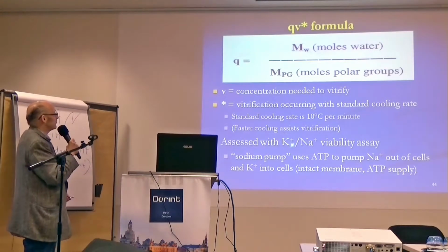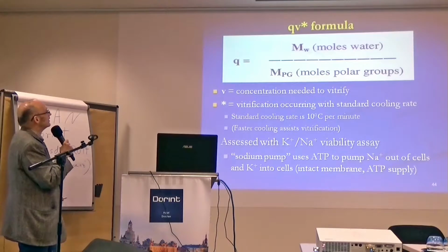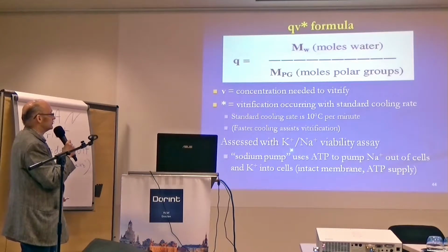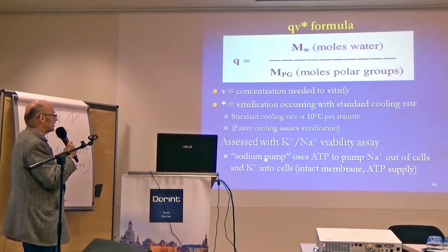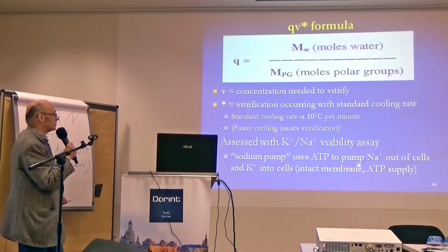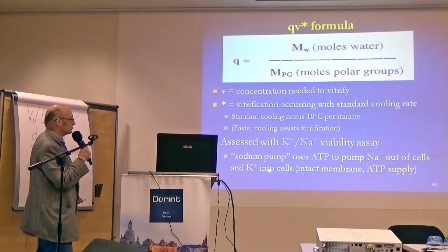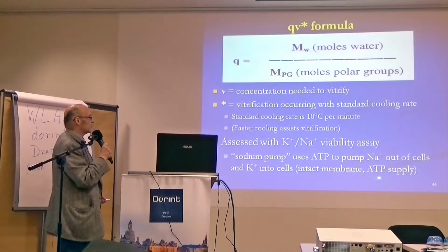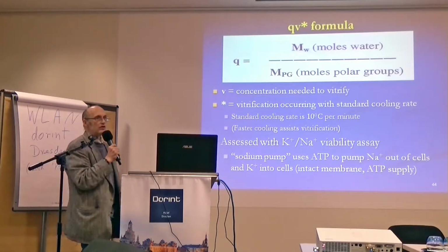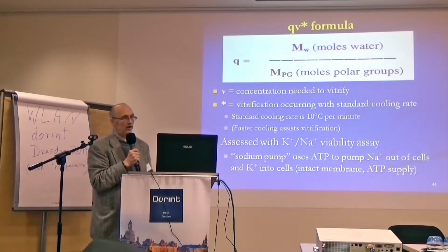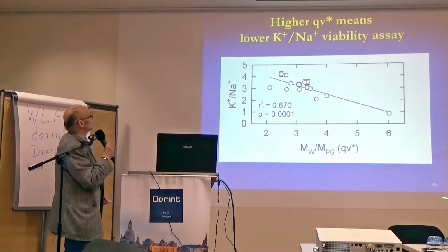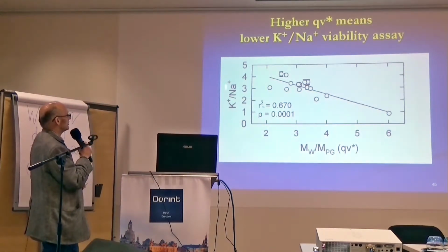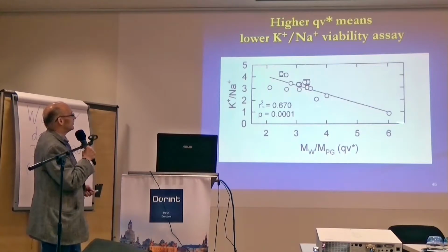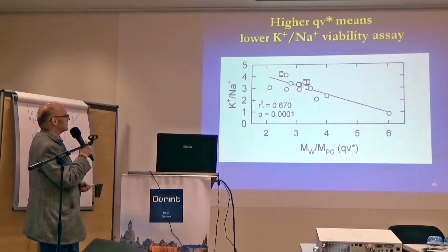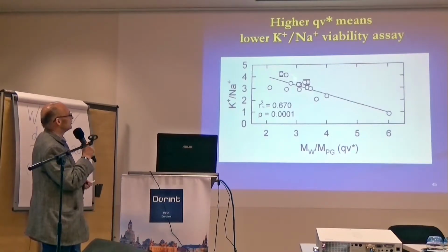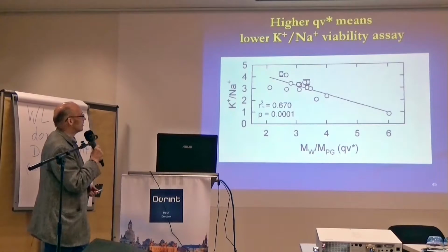And the assay for cell viability that's used is the potassium-sodium ratio. We've got a sodium pump in our cells that uses ATP to pump sodium outside of the cells and potassium into the cells. So if you've got an intact membrane and your ATP supply is working, you should have a normal potassium-sodium ratio. So here's a plot. There's the sodium-potassium ratio plotted against QV star, and this is the line that is used as the indicator of the QV star hypothesis.